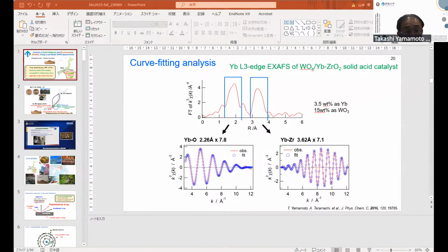Next, we apply inverse Fourier transforms to these regions like this. The oscillations and envelope function, or the frequency, differ. Near regions have low frequencies, but longer distances have high frequency. It changes like this. The top of the envelope function is around 5 angstrom inverse, which means different kinds of elements exist.